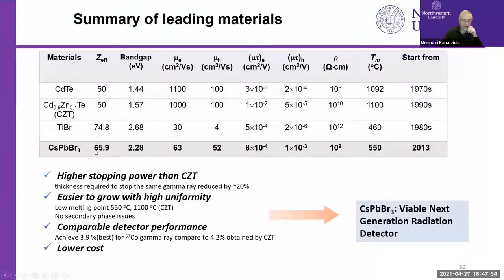There's nothing else except our material here, the perovskite, which has a gap of 2.28. It has mobilities of about 50 or 60 for both holes and electrons. The mu taus are also 10 to the minus 3. Actually, we have much higher values now. Resistivity 10 to the 9 or higher. And a nice, reasonable melting point. So I think this is quite promising as a viable next generation radiation detection material. And it also has lower cost because it's easier to grow. The materials are cheaper. Cadmium and tellurium are very expensive because they are 5/9 or 6/9 pure. Our material is cheaper and more of the material is usable.